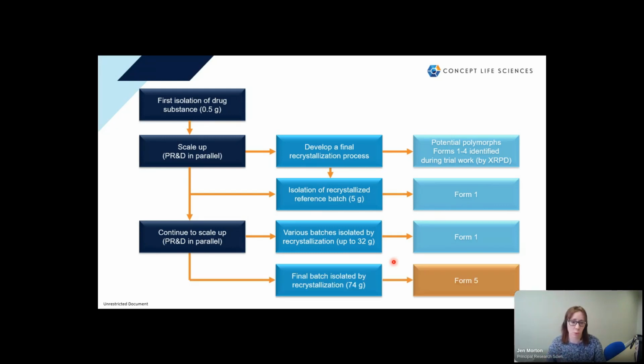And then we brought the rest of our material through to the end of our synthesis and put that through the final recrystallization. So 74 grams, just over double what we'd done before. Isolated the material, chemically nice and pure, but when our XRPD came back, we had a different form. It didn't match what we had got before. Not only didn't it match form 1 that we were hoping for, it didn't match any of the forms that we'd identified at the beginning.